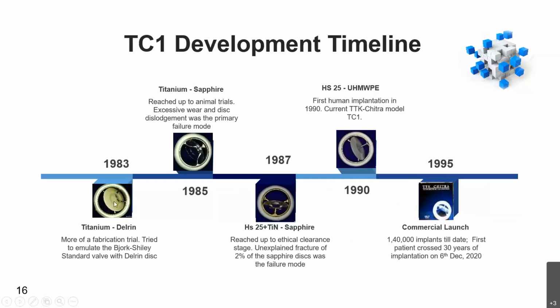Then for the disc, from Delrin we had already moved to a single crystal sapphire. The same single crystal sapphire prevailed in the case of the third model. But to our surprise, about 2% of the sapphire discs fractured in our test systems. And actually, we didn't have sufficient quality control strategies to screen out this 2% of sapphire discs. Because of this, even though this was a good valve and would have lasted about 15 to 20 years without any problem in the patient, we had to abandon this particular model.